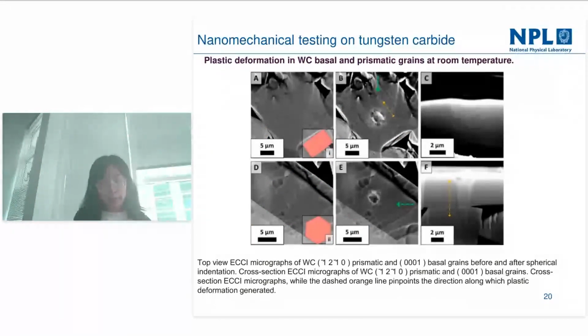In addition to the AFM scan, we also did ECCI, electron channeling contrast imaging, on both the surface and cross section of both the prismatic and basal planes before and after the indentation test. You can see the dislocation slip planes are quite consistent with the AFM observations of two-fold and six-fold symmetry.